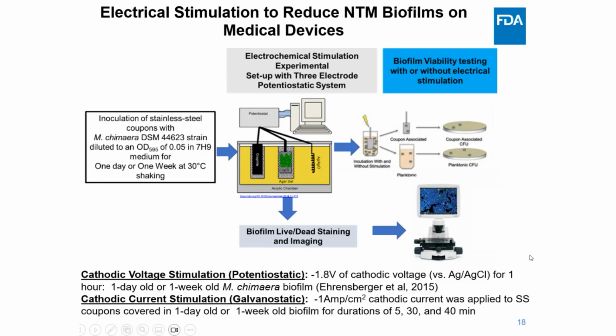So now we have introduced the concept of using electrical stimulation to disrupt NTM biofilms. Let's take a closer look at how the experiment was conducted. We began by inoculating the stainless steel coupons with a standardized culture of Mycobacterium chimaera strain, which is a slow-growing NTM species. And then biofilms were grown for either 1 day or 1 week in 7H9 medium at 30 degrees, shaking. After incubation, the coupons were gently washed in PBS and placed into this custom-built agar chamber designed for 3-electrode potentiostatic stimulation. To ensure uniform conductivity, PBS was added to each electrode well surrounding the coupon.